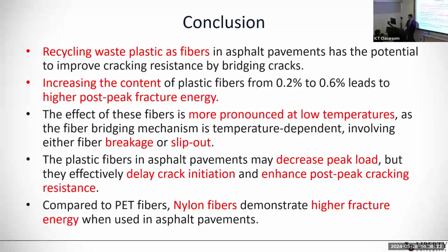And also, the impact of these fibers on the fracture energy is more pronounced in the post-peak area, because it holds these materials together after the peak load. And also the temperature. At the higher, intermediate temperature of 25 degrees Celsius, we saw that the fiber slid out, while at the lower temperature, we observed fiber breakage.